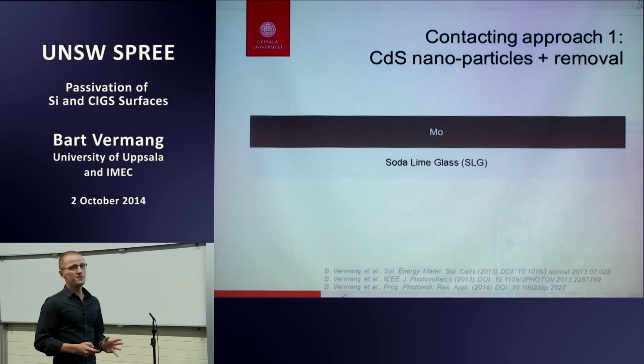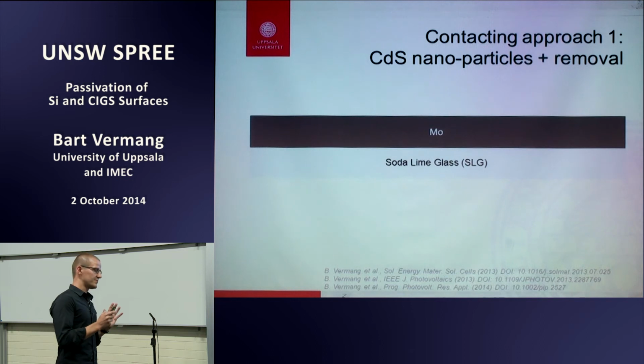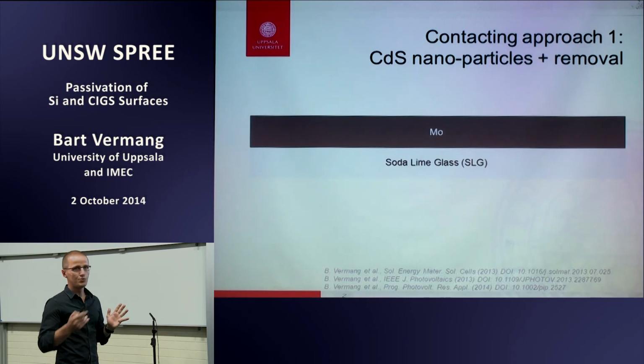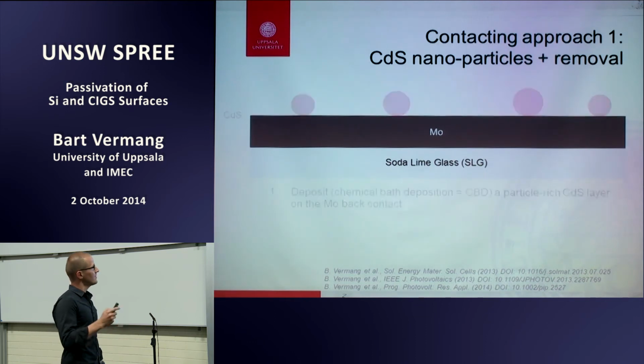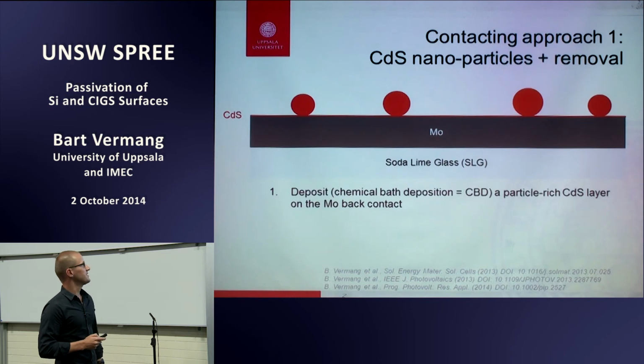So what we were aiming for from the beginning, starting from what they have in silicon and adapting it to the circumstances we have in CIGS, we were aiming for openings of 200, 300, 400 nanometer, and then a pitch, or distance between the openings, of 1 to 2, 3 micron. So what we did, in the first case, is we used cadmium sulfide nanoparticles.